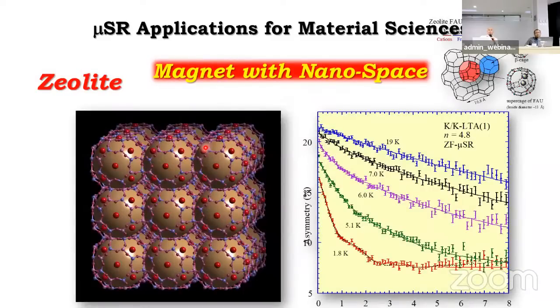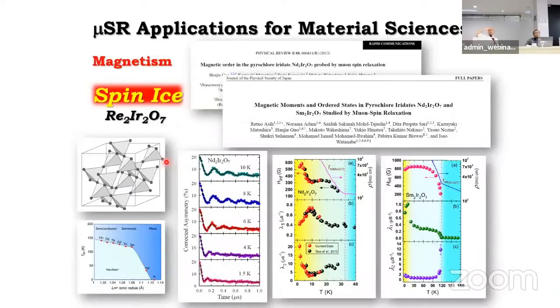So then this example is a zeolite system. Zeolite is used for toothpaste as well. And there are many zeolites, and many places where we are using zeolite. But zeolite has very small spaces around here. Then this collaborator can put the electron in here. Interestingly, this electron shows an ordered state. So this study is the first report to show such kind of magnetic ordered state in zeolite. However, this magnetic moment is very tiny. Unfortunately, neutron cannot pick it up. Too small. But even for a small magnetic moment, muon can easily pick it up. So that is one of muon's good points.